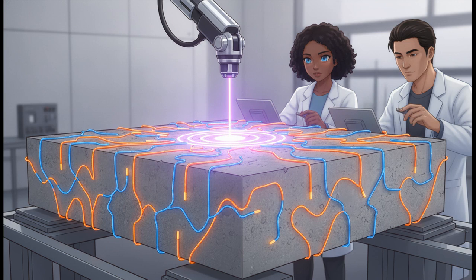And to make absolutely sure not a single piece of data escapes those flames, the specimens are going to be heavily instrumented. You can't just stare at a fire and know what's happening inside a rock, right? So they literally wire the concrete with 8 K-type thermocouples per test. Some go internally at mid-depth, some on the unexposed back face, and some right on the surface directly facing the fire. They're also using LVDT displacement transducers. These are highly sensitive devices that track the physical bending of the beam in real time, meaning they can detect a loss of structural integrity long before the whole thing totally collapses.